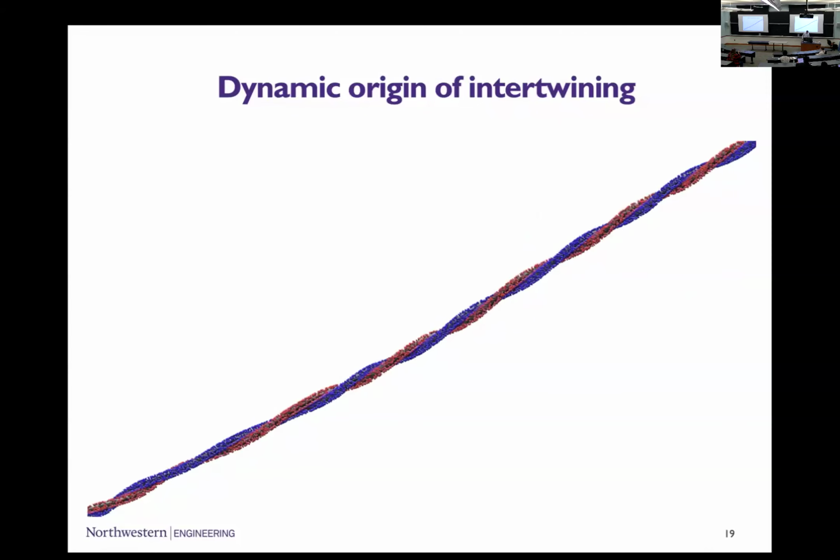And it's actually interesting to understand what's happening. For one thing, you see that on the lower left here, there's something going on that doesn't fit. And that's called the chirality defect. So these two chains meet, start twisting around each other, but they make a different choice in terms of helicity, like clockwise or counterclockwise, on one side of the crossing than on the other. It's kind of funny that it happens.